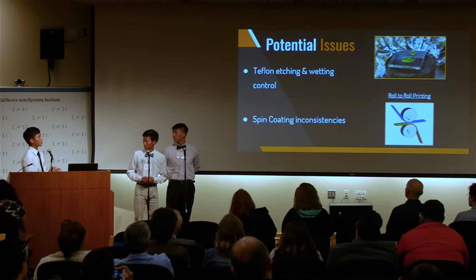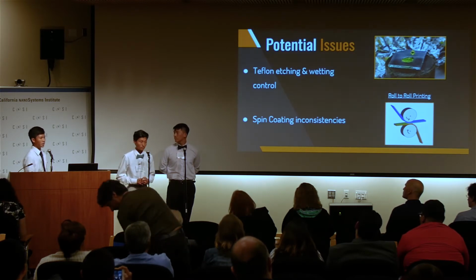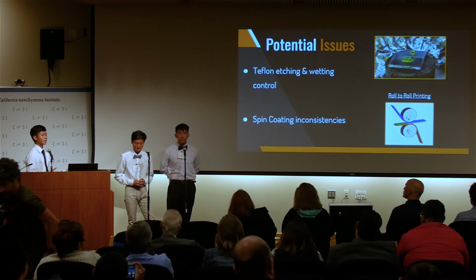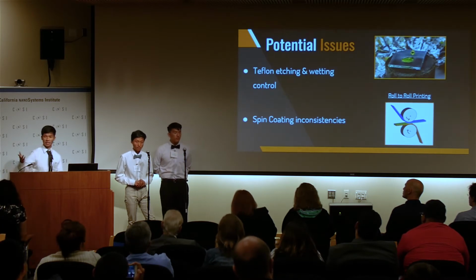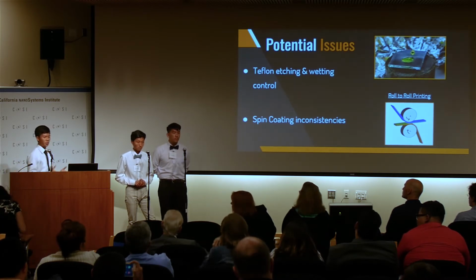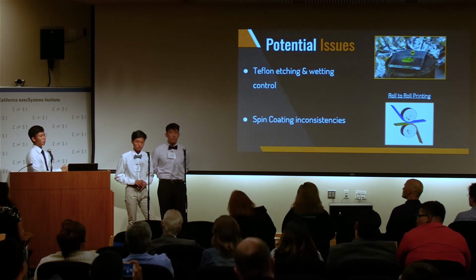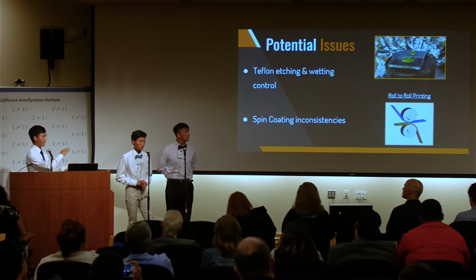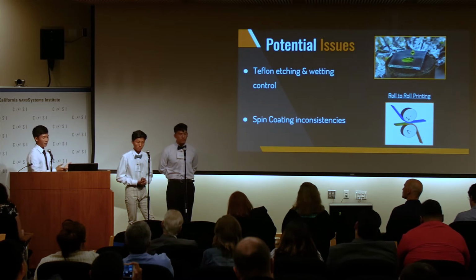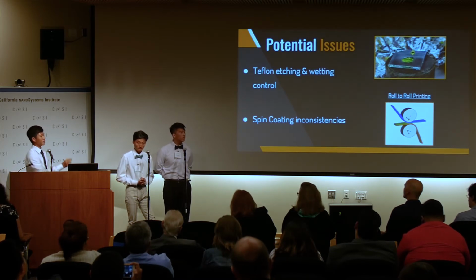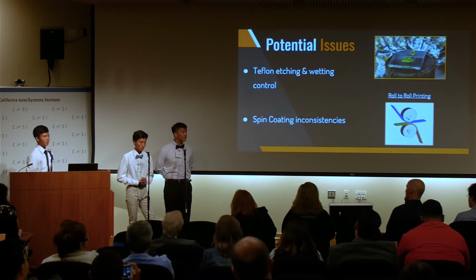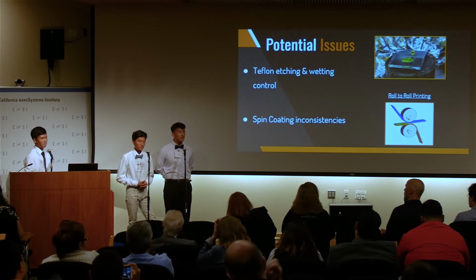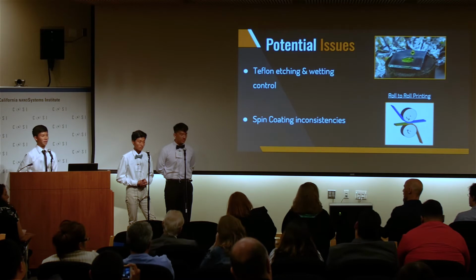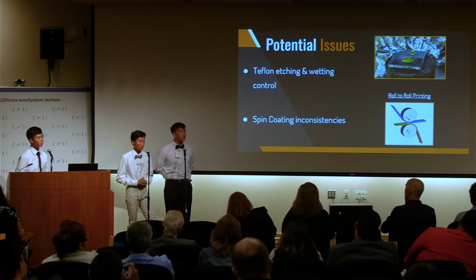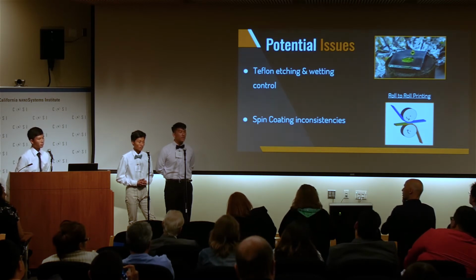Well, actually, roll-to-roll is an alternative instead of spin coating, because as of right now, you're just doing small samples. Like in Nick's lab, they're doing small little samples. But if you were to manufacture these, you can use roll-to-roll, which is a very efficient, fast way to add layer after layer. And that is just a better alternative because you can choose the thickness and everything you want. Definitely much faster, much cheaper, and more efficient. Exactly. So I guess it's been shown, and there are no major hurdles in achieving that goal in terms of roll-to-roll printing of the perovskite?